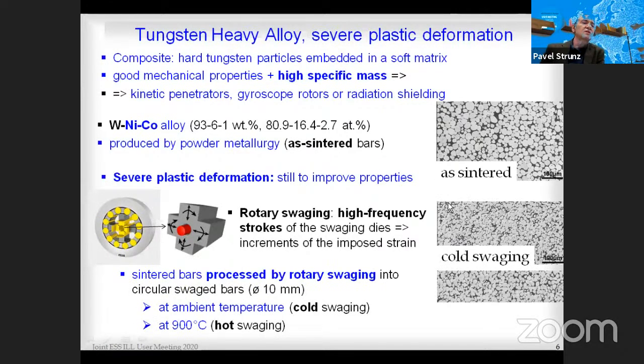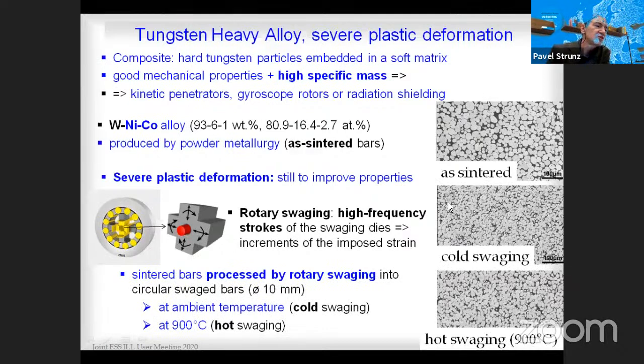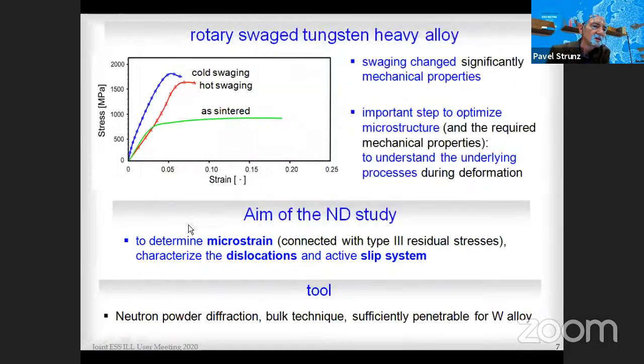Properties of such alloy can still be improved by severe plastic deformation. In our case, we used a method which is called rotary swaging. Sintered bars were processed by rotary swaging at ambient temperature and at 900 degrees centigrade. Swaging changed quite significantly the mechanical properties, which can be seen from this stress-strain curve. An important step to optimize microstructure is to understand the underlying processes. And that was the aim of the neutron diffraction study, to determine microstrain, and characterize the dislocations and active slip system.